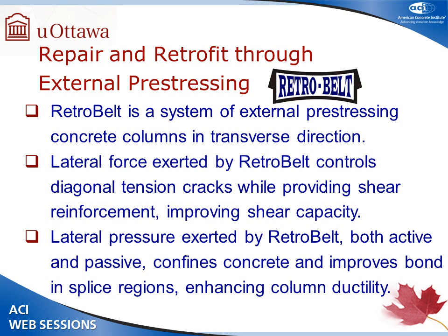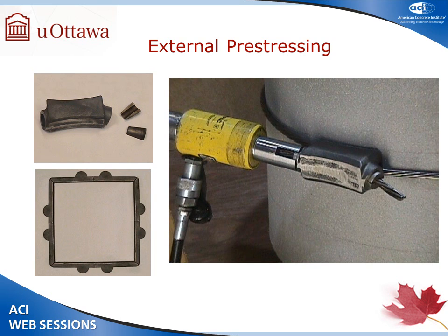All other jacketing techniques, whether steel jacket, concrete jacket, or FRP, have passive pressures. But in this case, we are in fact able to recover some of the aggregate interlock resistance, the shear resistance of concrete, because we're essentially squeezing the column, as well as improving bond in the splice region. The technique is obviously well established, and we're using no new material. We're using 7-wire strands. The only thing that is challenging is the anchors.